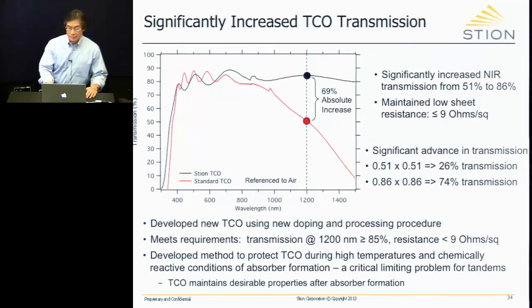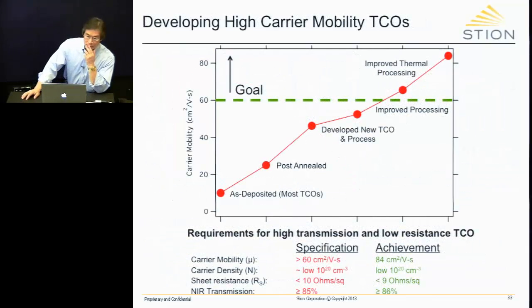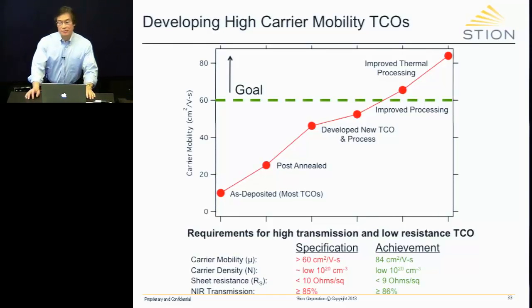Yes? So you're showing an 86% transmission. Is that for a single film or just stacked? It's just a TCO. It's just a TCO in the near infrared at 1200 nanometers. So when you're stacking 3 of these to do your tandem structure, that means you're getting 65% or so. I'll show the calculation in the very next one.